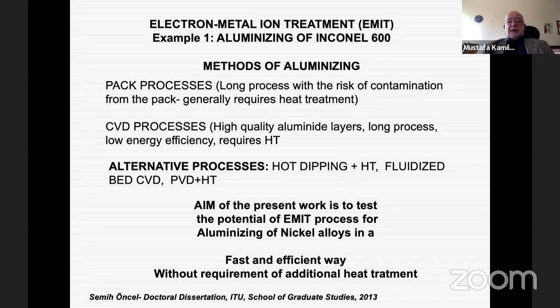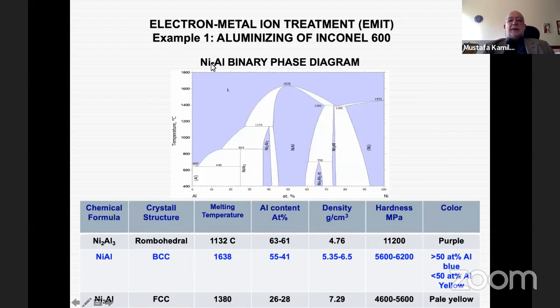So we started to try to apply an alternative method for aluminizing of nickel alloys by this method that we have developed. We named this method electron metal ion treatment because we are both utilizing the electrons and the metal ions that are present in the cathodic arc plasma by using an alternating current bias surface.